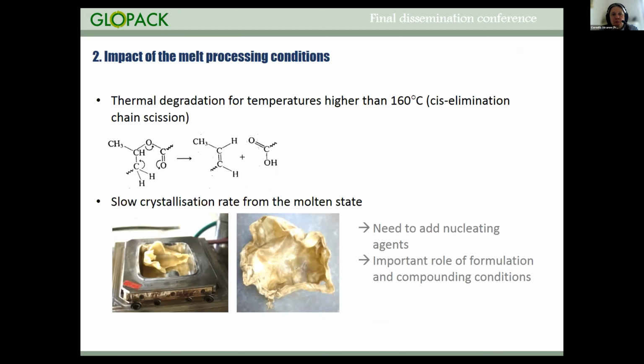So the PHBV material is very sensitive to high temperatures. At temperatures around or above 160 degrees, chain scission occurs. You can see here the formulas on the slides. And we really have to avoid the cut of the chain and the production of small molecules. And due to this thermal sensitivity, the processing window between melting and degradation is narrow and has to be adjusted really well. And on the other side, we have the slow crystallization of PHBV.